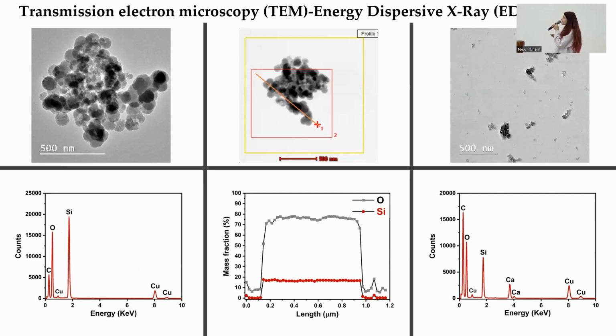Quasi-spherical silica nanoparticles of about 50 nanometers were observed by TEM analysis. The STEM module allowed us to achieve a linear profile of 50 spectra that can be summed up to give a global spectrum of the analyzed area. And we can see that the main elements are silicon and oxygen, and there are no major variations, meaning that our nanoparticles are homogeneous. And also, you can see that our nanoparticles were mostly agglomerated, so a stabilizing agent was necessary.